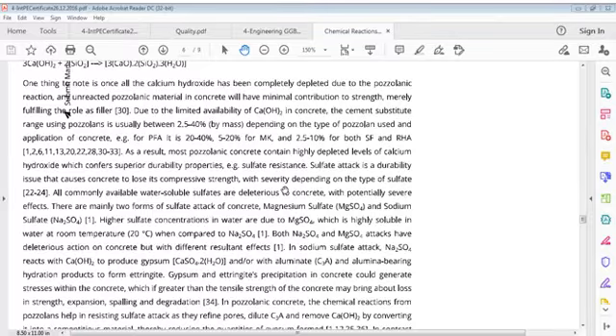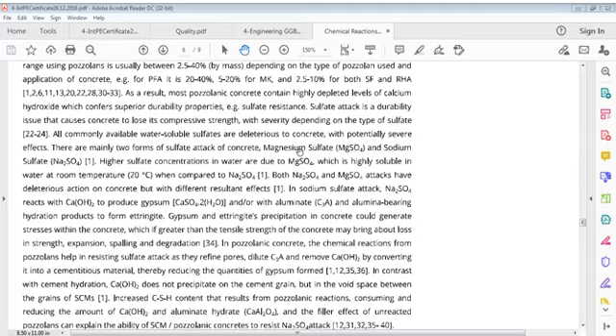For PFA, pulverized fuel ash, it is 20 to 40%, 5 to 20% for MK, metakaolin, and 2.5 to 10% for both silica fume and RHA. As a result, most pozzolanic concrete contains highly depleted levels of calcium hydroxide, which confers superior durability properties, namely sulfate resistance.